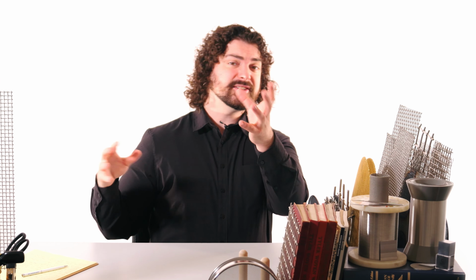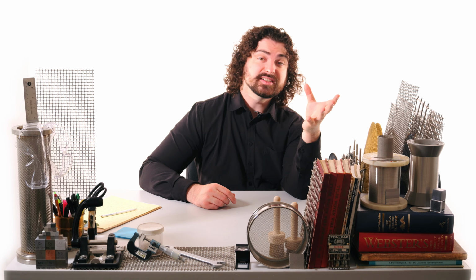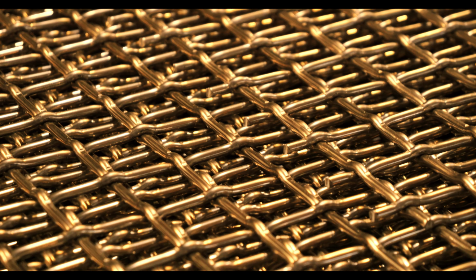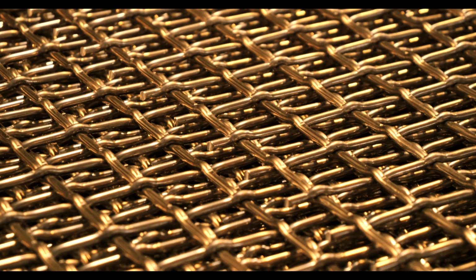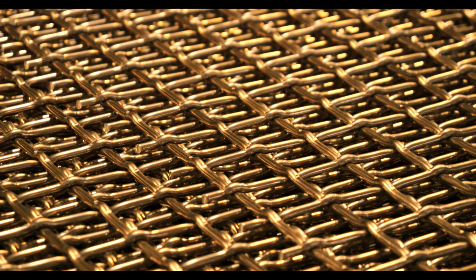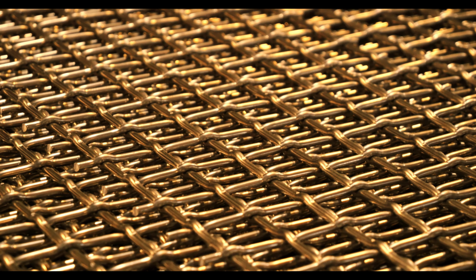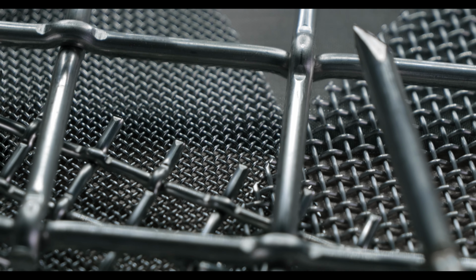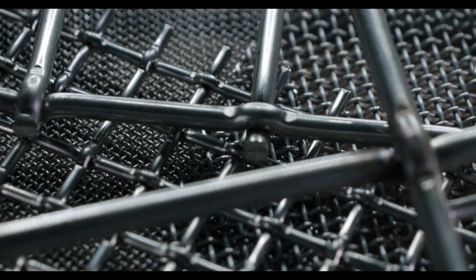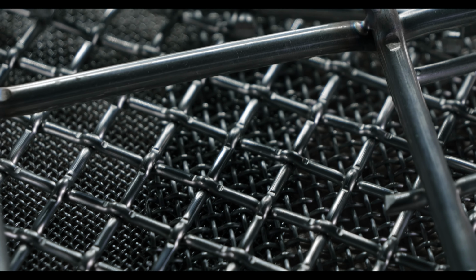And material chemistry is as important as pore geometry. Gas streams often contain halides, sulfur compounds, or acidic dew points that can corrode standard stainless steels. In systems insulated above the acid dew point, 316L stainless steel may suffice, but harsher conditions do justify high nickel alloys such as Inconel or Hastelloy. These alloys form protective oxide layers that resist scaling and spallation during thermal cycling, helping to extend the life of the filter and reduce downtime. Selecting the right alloy upfront prevents costly retrofits and ensures compliance with emission standards over the long term.